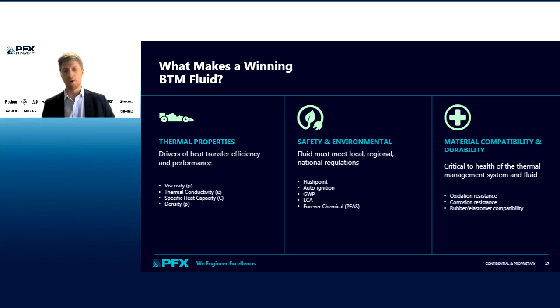If you don't have good corrosion protection or material compatibility, your fluid can degrade the components which are meant to contain it, and this can lead to leaks, right? You can have buildup of corrosion deposits, which can lead to blocks, or you can have corrosion through a material, which leads to a leak, which in a worst case scenario could leak into a battery pack and cause a fire. So these are the three things we care about when we're starting at the drawing board to put together a new formulation.